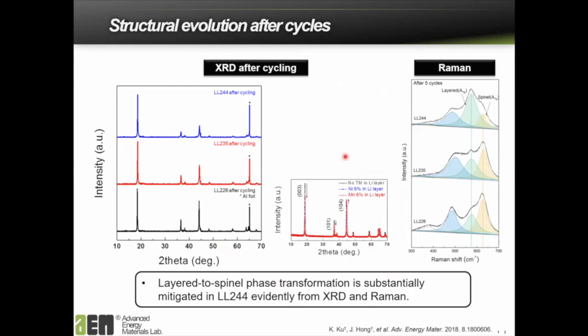And after the cycles, we analyze the samples to see how the formation of disordered or spinel-like structures were affected by the presence of the redox buffer. And these experiments confirmed that the phase transition was also substantially inhibited with the sample with the redox buffer in here.